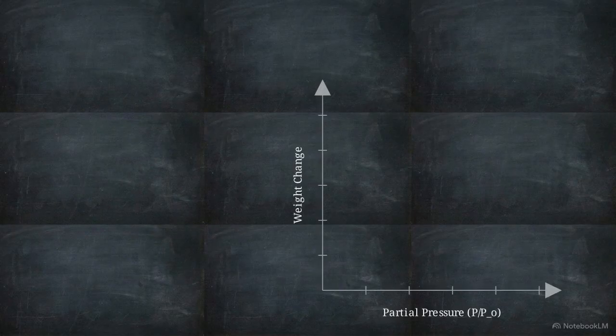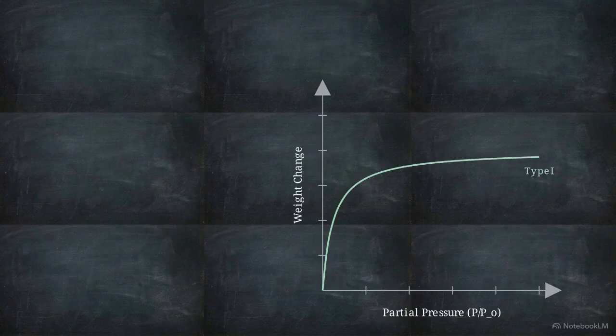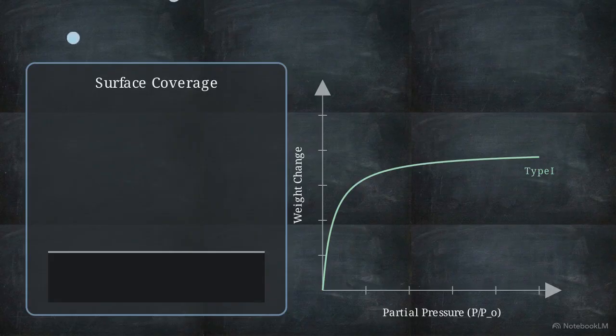This plot illustrates a Langmuir, or type 1 isotherm. Notice how the mass uptake rises sharply at low pressures, but quickly hits a hard, flat plateau. That plateau confirms the surface is completely saturated. It represents monolayer coverage, meaning every accessible binding site on the solid is occupied by exactly one gas molecule. No further increase in pressure will force more gas onto the solid.